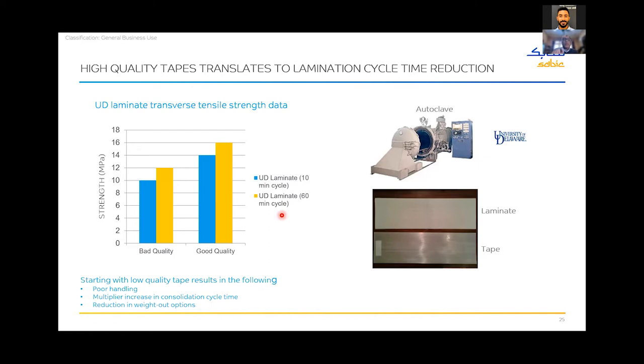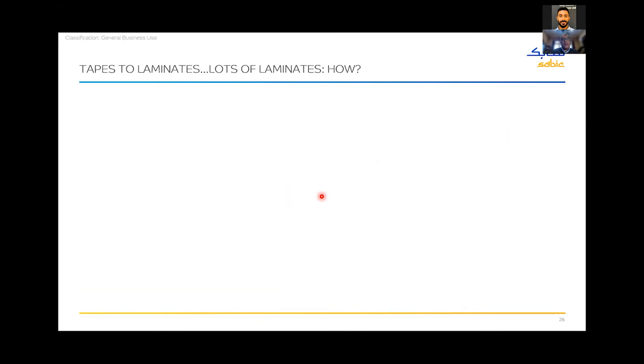Because remember, you're dealing with thermoplastics. And thermoplastics, by definition, are extremely viscous viscoelastic materials. So to get out air bubbles from deep inside that tape, inside the laminate, and extract that out of the laminate so that you get the highest performance at the end, can sometimes even make it 6x, 7x the cycle time, which is absolutely something we don't want. Because we said the value proposition of thermoplastics is in and out fast, right? Shrink down that cycle time. So my point here is making good quality feedstock materials like tapes is absolutely crucial for you to accomplish that value proposition at the end of the day. And here we worked a lot with the University of Delaware and the composite materials lab there.